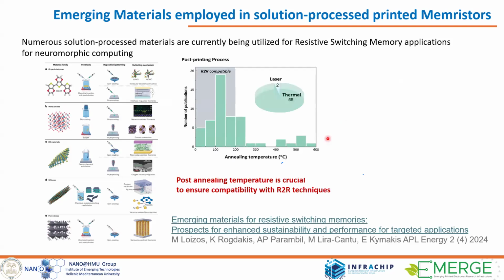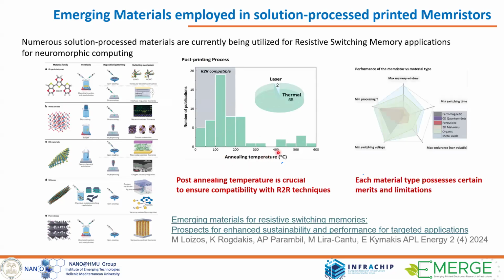So for this kind of printable devices, the annealing temperature is very important. This is the limitation, because all the deposition is done at low temperatures, even room temperature. The only demanding point is the annealing of the layer. That should be kept below 200 degrees to make it possible to fabricate a device on a flexible substrate. And of course, in this paper, we show that each material has advantages and disadvantages. So we implement a benchmarking between the various emerging materials in terms of maximum memory window, minimum processing temperature, minimum switching voltage, and maximum endurance or durability of the memristors.